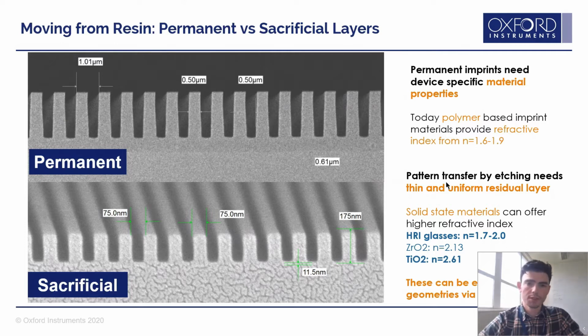So instead, we have to do our stamp into a resin as a sacrificial layer. The resin now acts as a mask to allow us to etch the final product. So we're adding on another fabrication step at the end to allow the use of these high RI materials. And we can do this using ion beam.